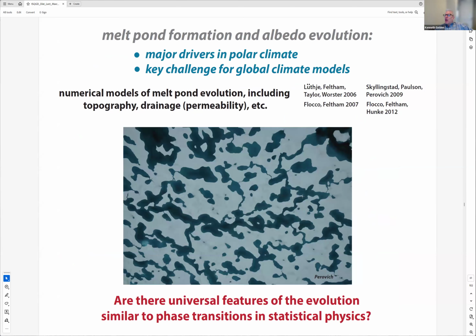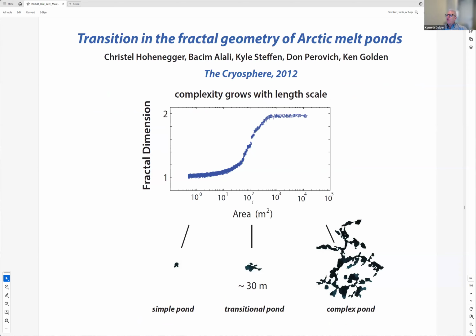Okay, so another area that we've studied a lot is melt ponds, as I've mentioned before. And I looked at these and said, hey, they look like fractals. And so that's what first got us into fractals, actually. And we discovered that melt ponds exhibit a transition in the fractal dimension around 100 square meters from 1 up to 2, where the boundaries behave like a space-filling curve.